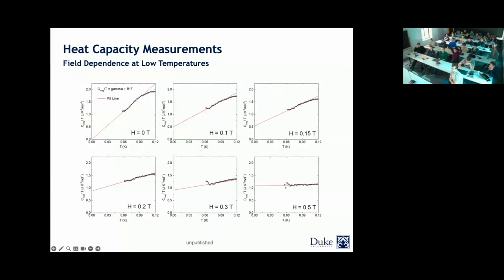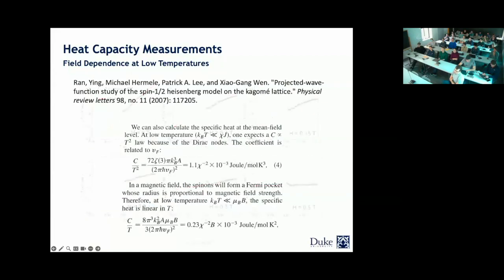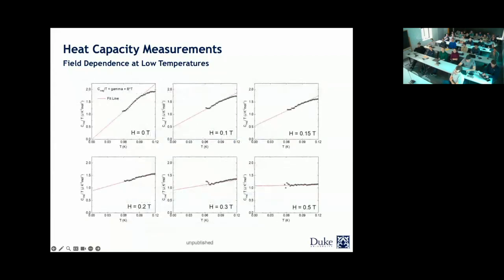Here we actually started to go even higher in field. Here you're looking at the extrapolations at 0, 0.1, 0.15, and so on. You can see that when it gets to 0.5 Tesla, it starts to deviate from the physics of the Dirac quantum spin liquid. Excuse me? If you go look at those plots, those little wiggly tails at the lower temperatures, is this because of the subtraction scheme? This is because of the subtractions, yes, exactly.